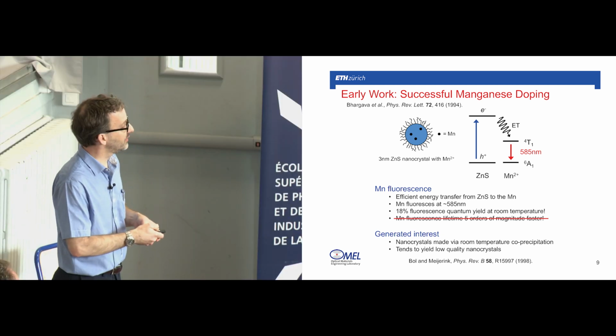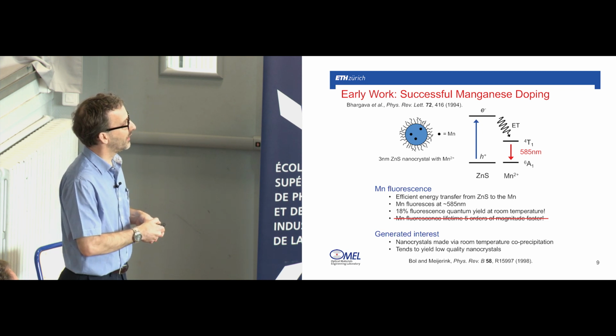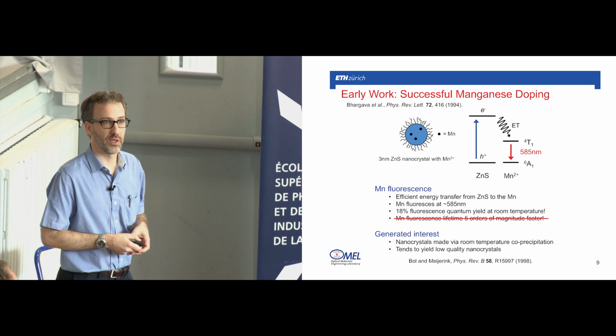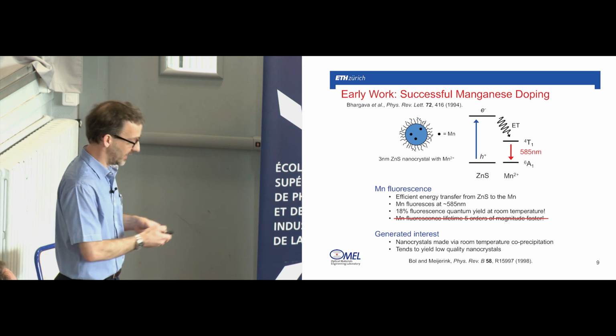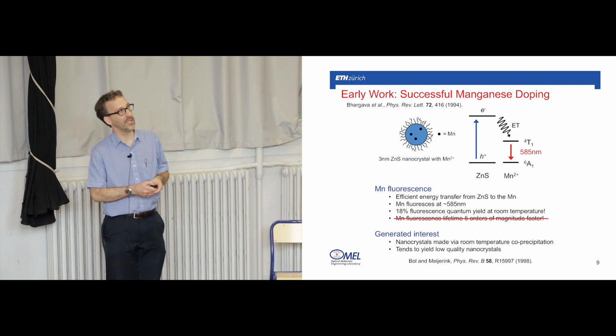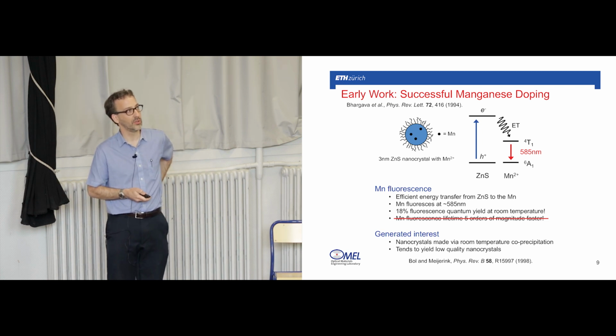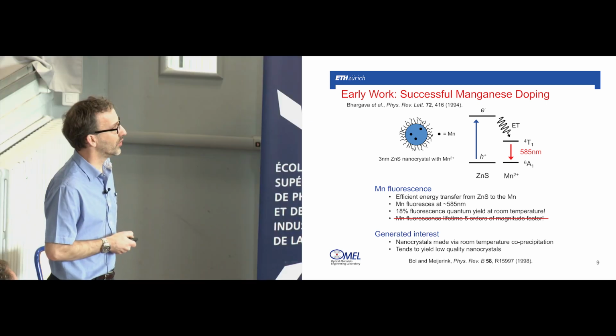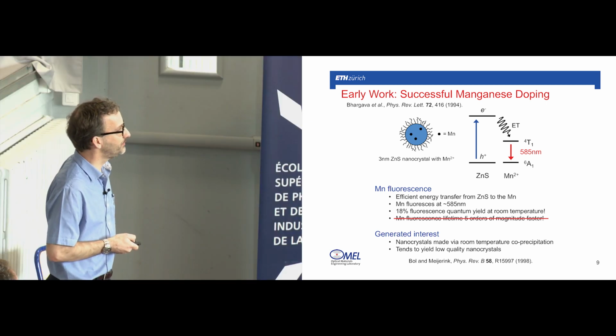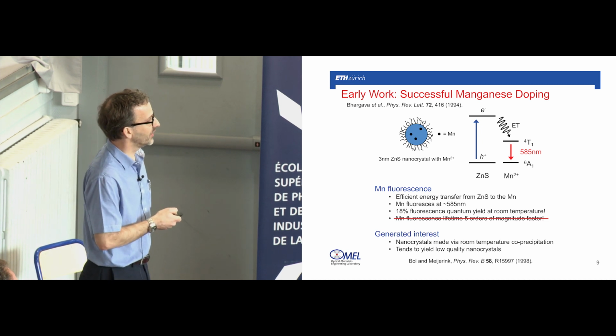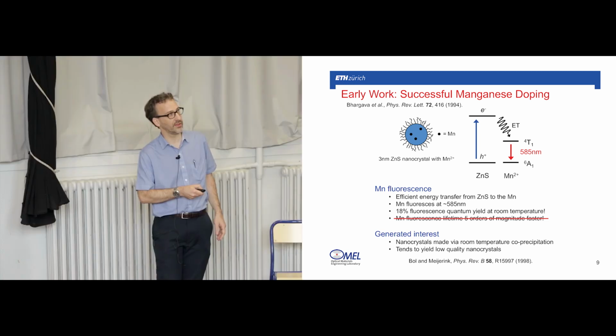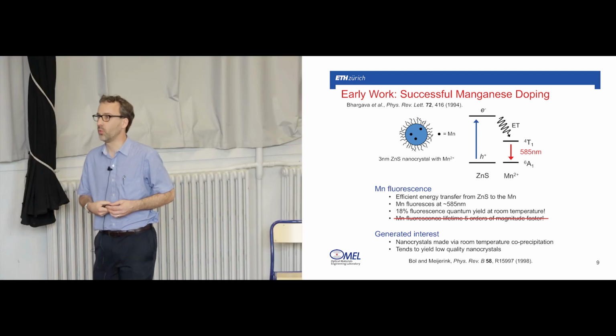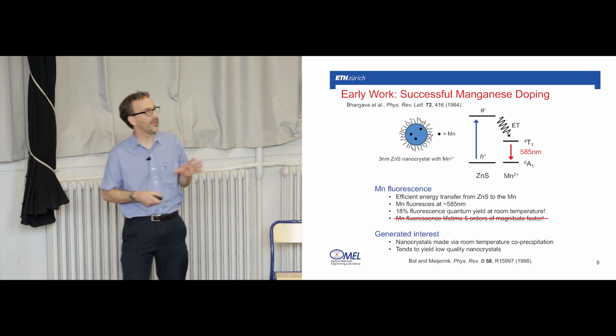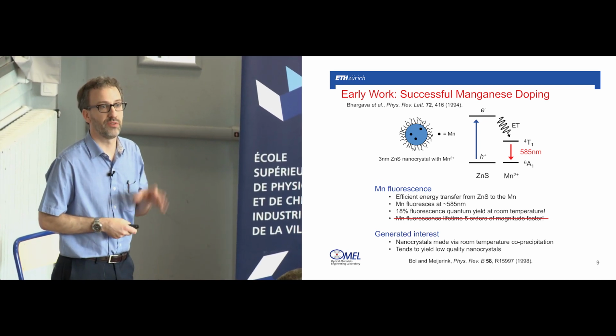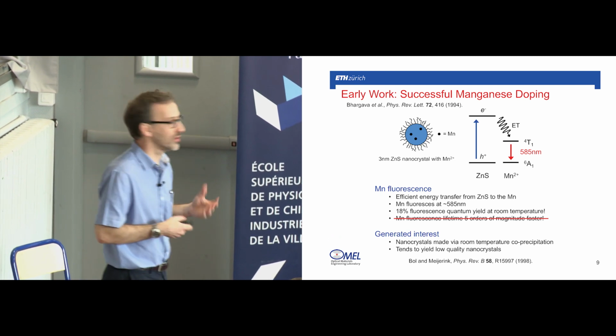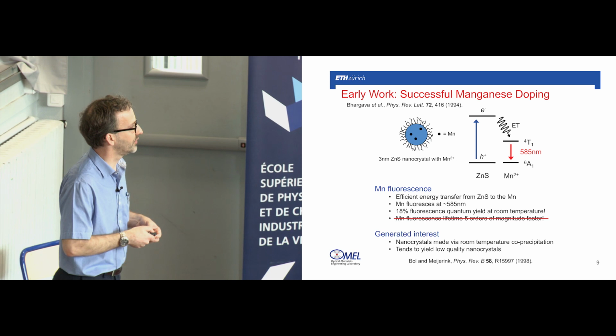Why it was interesting is that these particles, if you excited them with light, without the manganese, you didn't get any photoluminescence, so they were very poor particles in terms of their inherent photoluminescence. But with the manganese, you got very efficient energy transfer to the manganese, and then it fluoresced in the red-orange through an internal transition of the manganese. The reason it got everybody excited was that the fluorescence quantum yield was really quite high. It was reported to be 18%, which, if I remember, at that time in '94 was the highest fluorescence quantum yield of any particle, doped or undoped. So it really started to make people think about what the possibilities of doping might be.